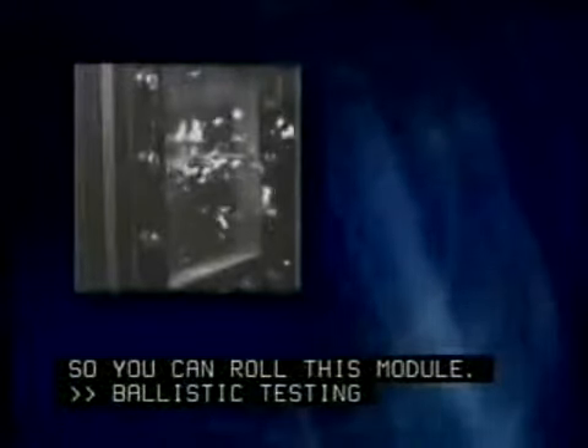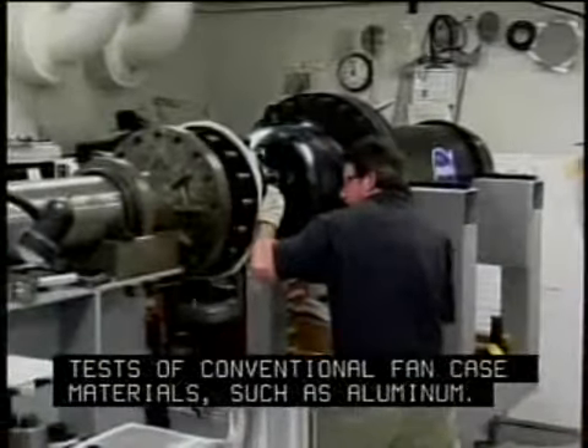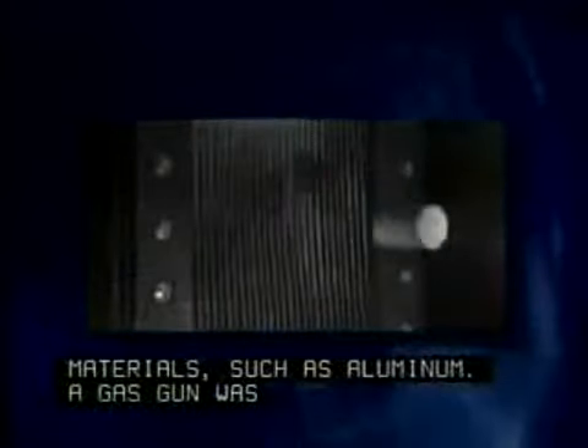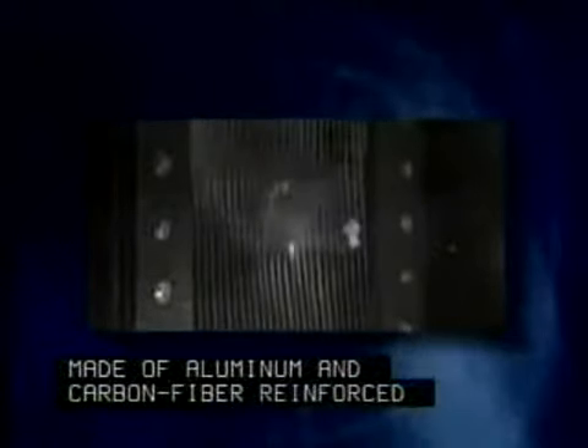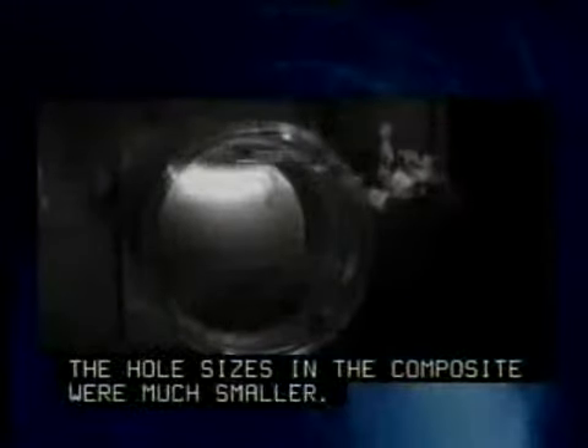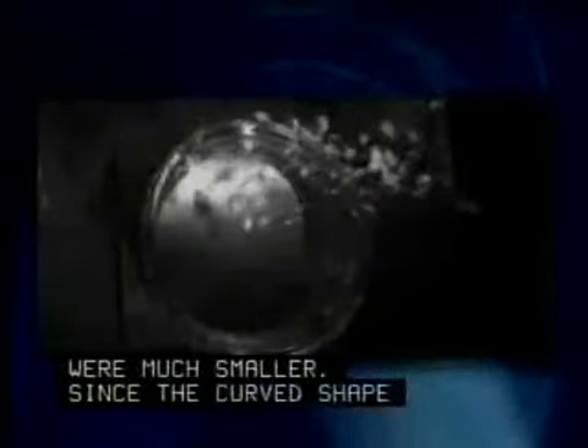Ballistic testing of the composite materials used in these new fan containment cases began with the damage testing of flat panels of the composites and comparing the results against tests of conventional fan case materials, such as aluminum. A gas gun was used to shoot metal blade projectiles simulating fan blades at panels made of aluminum and carbon fiber reinforced composite. The hole sizes in the composite were much smaller. Since the curved shape of the fan case helps reduce stress levels after a blade-out event, this was encouraging to investigators, and the research and development went forward.